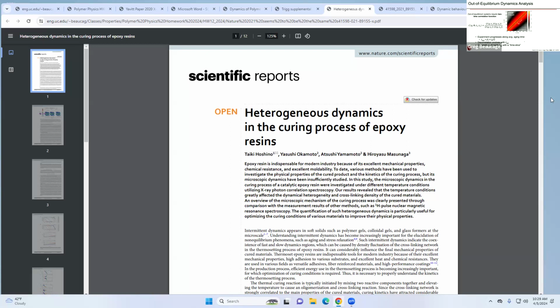Anyone have any idea what's going to happen if we have an out-of-equilibrium system? What do you think this figure is going to look like? Close. There will be some asymmetry in it. You will still have the same behavior on each side of the diagonal, but what you'll see is that it now bifurcates out and changes as you go along that diagonal. The color here on the scale bar is the amount of correlation that we have. In these systems, our system is decorrelating very quickly, changing from red to gray very quickly. But as you see, as we go out in time, that correlation starts to hold out for much longer time periods. So it stays correlated until longer times.